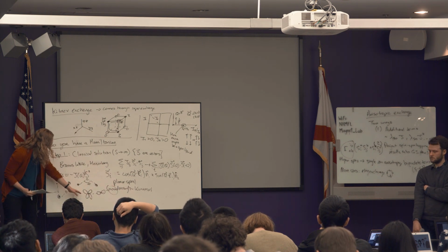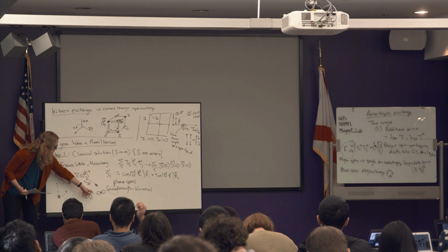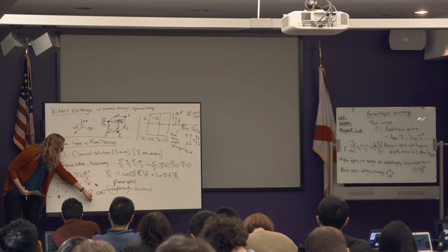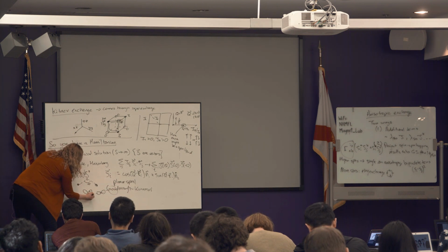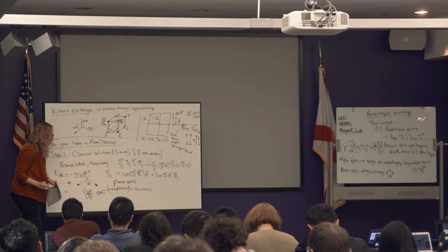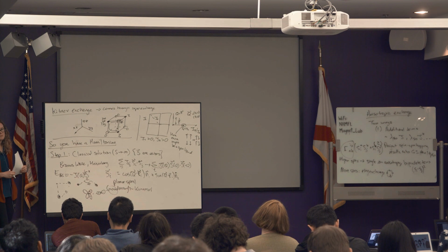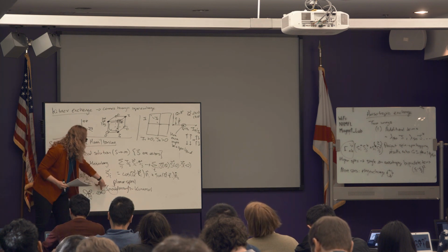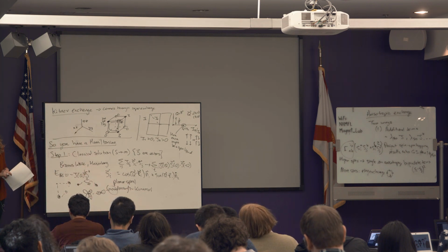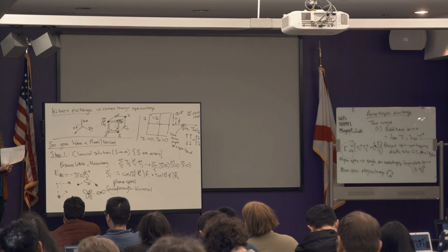So here, before when we drew it, this lobe was totally aligned with this. Whereas here now, this is going to be plus, and this is going to be minus. And so you have to be more careful, and that will actually give you a ferromagnetic exchange. So again, if you look up the Goodenough-Kanamori rules, you'll see the discussion of this there.